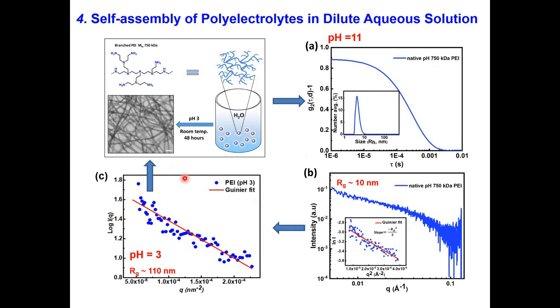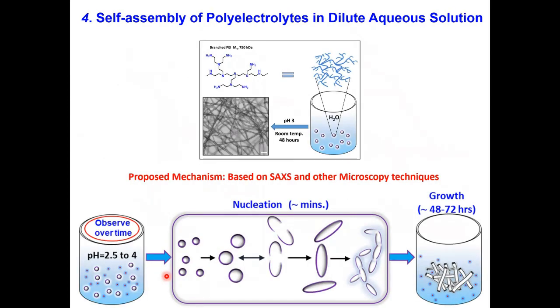And this is the data which shows that at pH 3, at the initial stages of formation of these fibrils, this 10 nanometer Rg structure actually forms 110 nanometer size objects. So the radius of gyration actually increases. That means they are aggregating in some sense and forming these structures. So this cannot really be probed by electron microscopy in real time. Based on small angle X-ray scattering, we propose a mechanism that you have initially smaller chains which become larger, and then they elongate and form these bigger tubule-like structures. Okay, the last example I want to give you, I'll take only a minute or so.